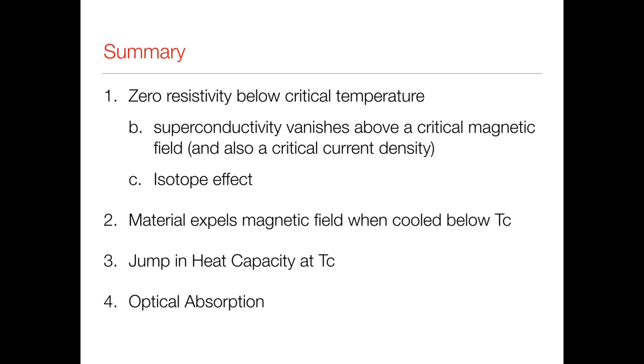We noticed there was an isotope effect, and we can understand that because we found that our superconducting transition temperature was related to the Debye frequency, and the Debye frequency was related to mass. So we understand the isotope effect. We knew experimentally the Meissner effect, that the material expels the magnetic field when cooled below the transition temperature, and we understood that in terms of the rigidity of the wave function, which led to the London equations, which predict the Meissner effect. We've also found that it can be more complicated in, for example, type 2 materials, where we get a phase in which the magnetic field can penetrate and it's not a perfect diamagnet.